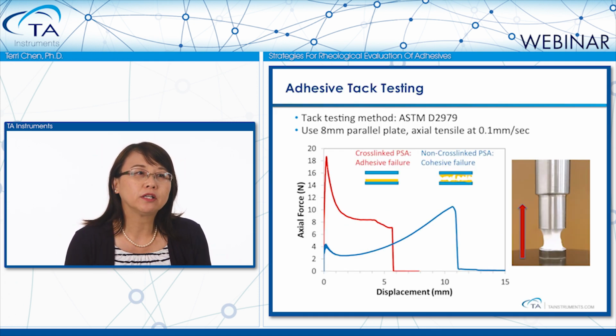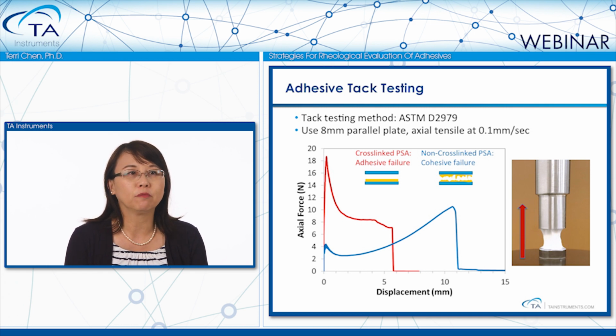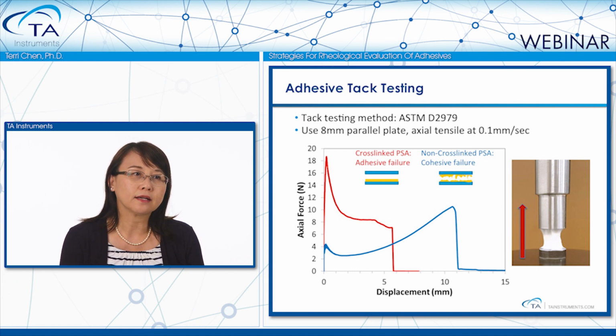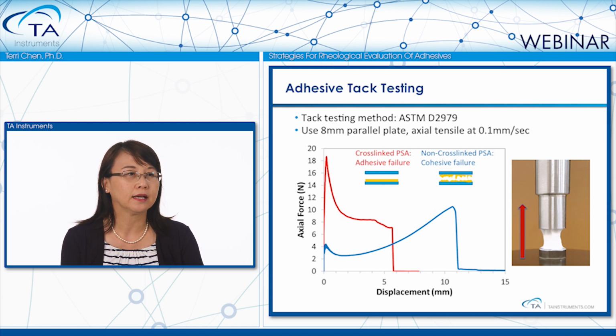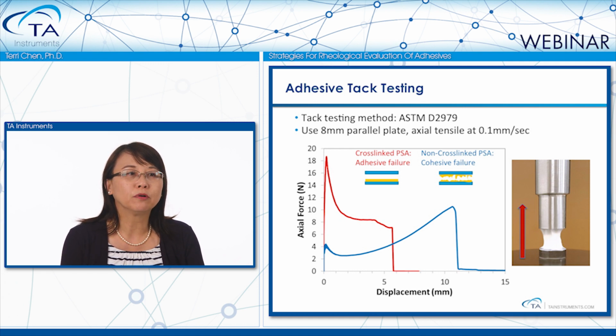One of the most commonly used methods for evaluating the tack performance of a pressure-sensitive adhesive is described in ASTM D2979. This test can be conducted on a rotational rheometer using an 8 mm parallel plate geometry. We place the sample between 2 parallel plates, apply a certain pressure for a short time, and then we pull off the plate with a speed of a certain millimeter per second, such as 0.1 millimeter per second. The maximum force that is required to pull the plate away is defined as the sample tackiness.